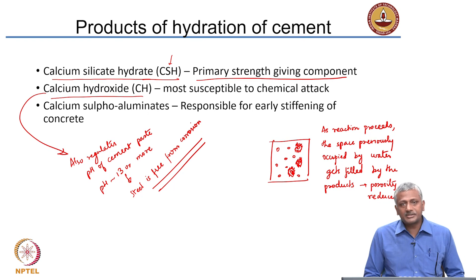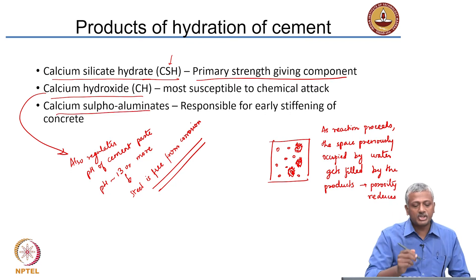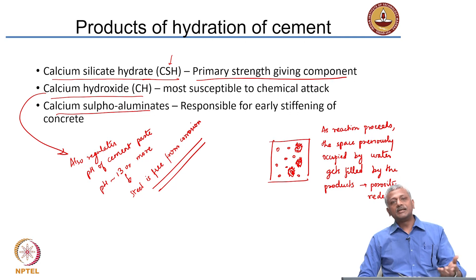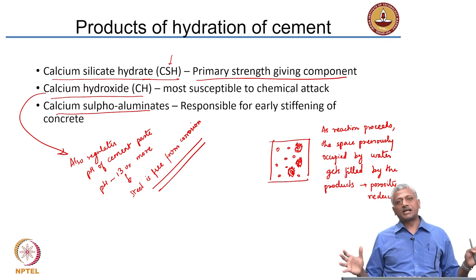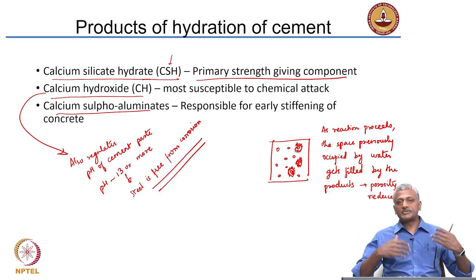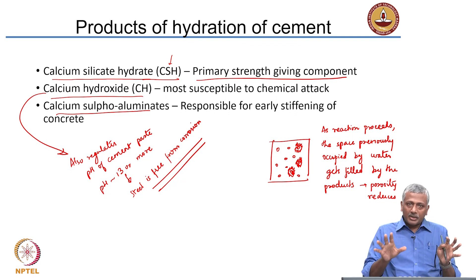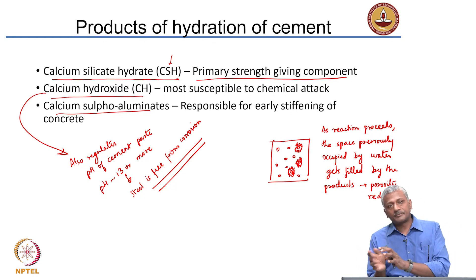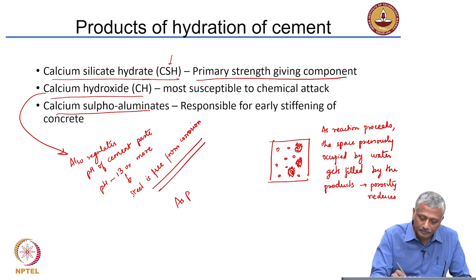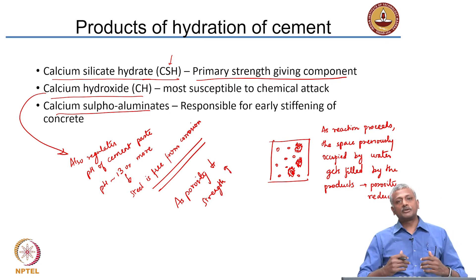When the concrete produces a highly alkaline environment, it protects steel from corrosion. When conditions reduce this alkalinity, you will get corrosion of steel. So you want this highly alkaline environment regulated by calcium hydroxide to be present. The calcium aluminates react with sulphate — since sulphate controls the rate of reactivity of aluminates — and form calcium sulphoaluminates, which cause initial strengthening and stiffening. Long-term strength gain is due to CSH. As porosity reduces, the strength goes up.